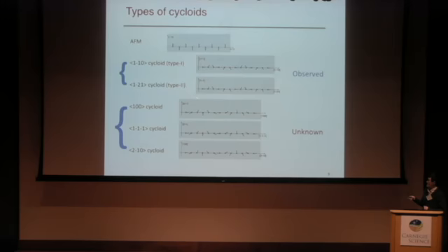So just to mention that in total, we have found 6 different types of magnetic structures, including the AFM and type 1 and type 2 cycloids that were observed in experiments before. We also predict 3 new types of cycloids, which were not known before. The difference between these 3 new types of cycloids and the known ones is that if we sum up the 3 indices of these numbers, it is an odd number instead of an even number, which means along the propagation direction, these 3 cycloids will be the antiferromagnetic cycloids instead of the ferromagnetic one.